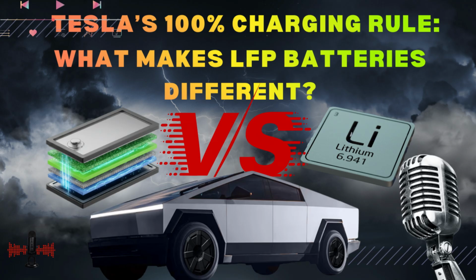It really does. And this structural difference entirely reverses the golden rule of battery care. For LFP owners, the advice isn't to avoid 100% charging, but to regularly charge to 100%. That step is a necessary calibration for the battery management system. That wide, shallow swimming pool. Exactly. To keep its range estimates accurate, which ensures reliability, not harming the battery's durability. And ultimately, LFP makes the vehicle a superior long-term financial asset. It virtually eliminates major capacity loss, and it defers that catastrophic future risk of battery replacement far beyond the typical ownership period. It's a design strategy that openly prioritizes generational longevity over flashy, short-term performance gains.